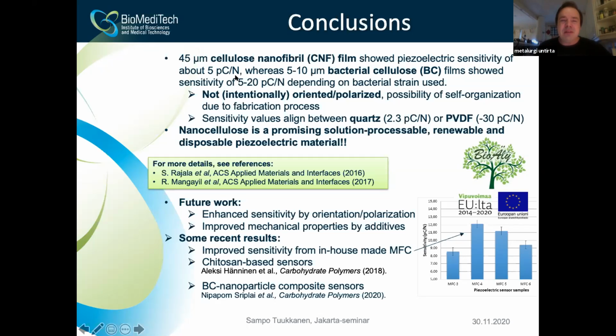So we got a little bit lower values for these wood-based cellulose films, and the bacterial cellulose films got a little bit higher. And here we didn't use any polarization or orientation; the piezoelectricity is only based on the natural orientation of the films. If you compare with the conventional piezo material developed a long time ago, quartz, it has a lot lower piezo factor in comparison to these nanocellulose films.